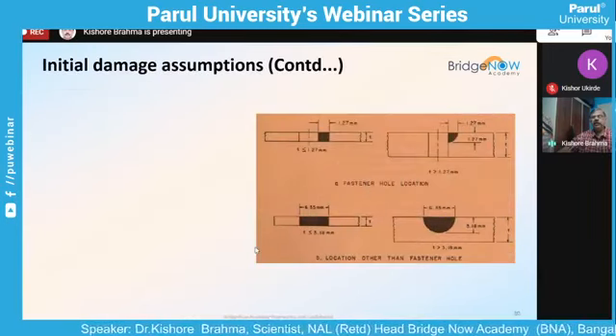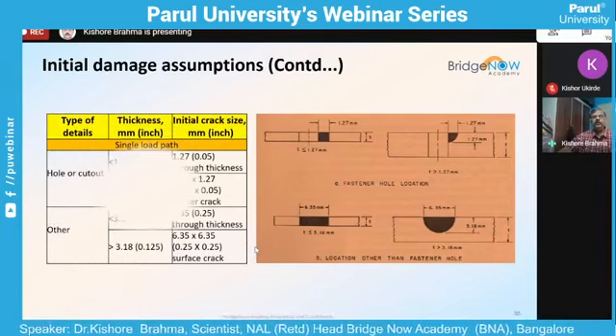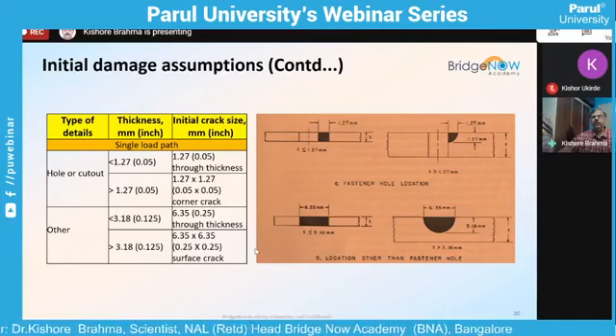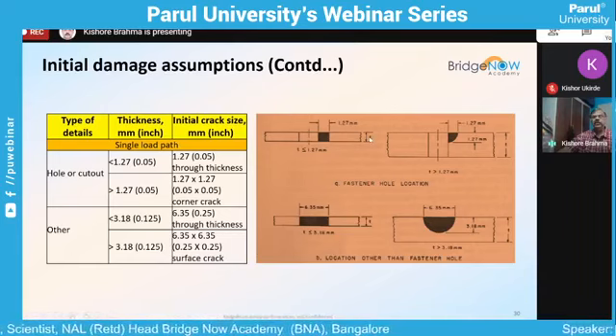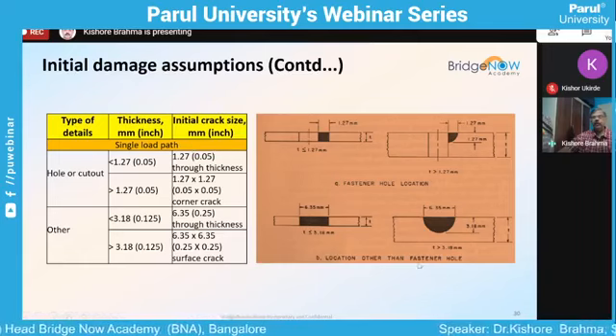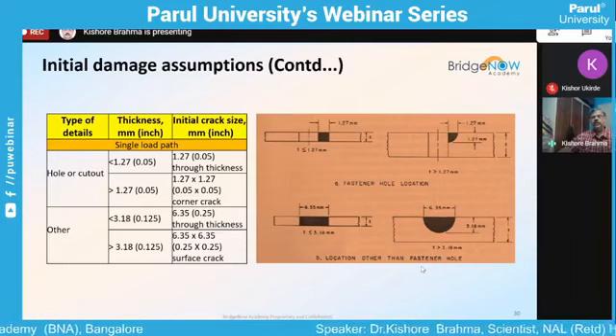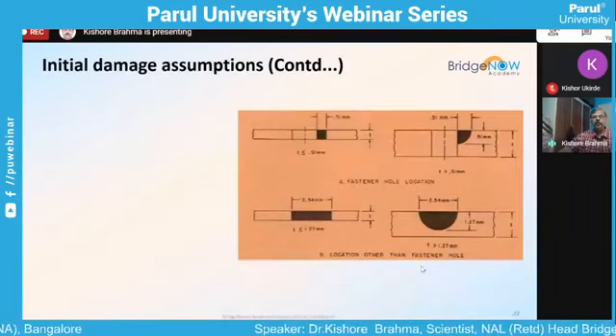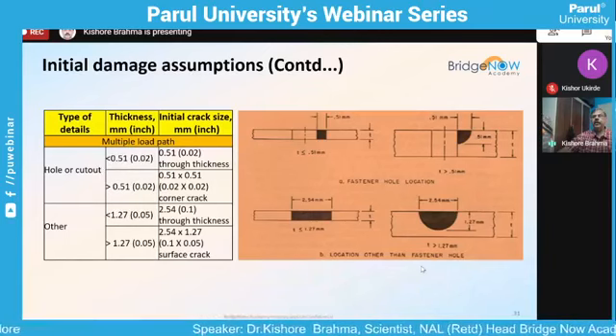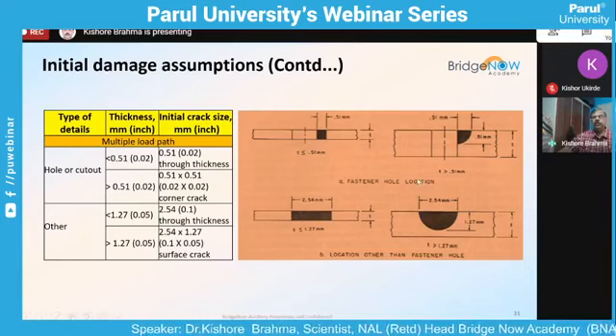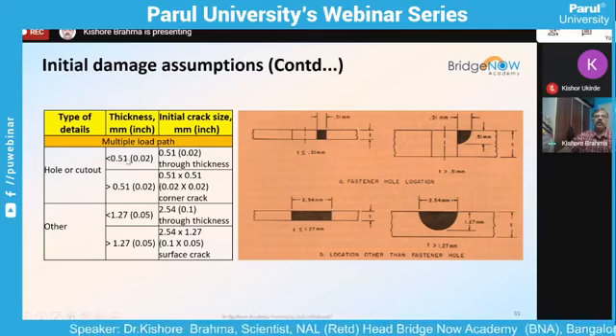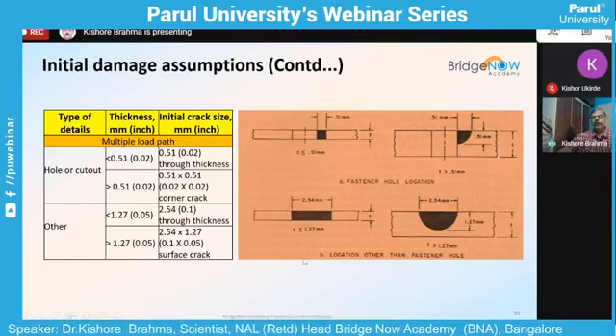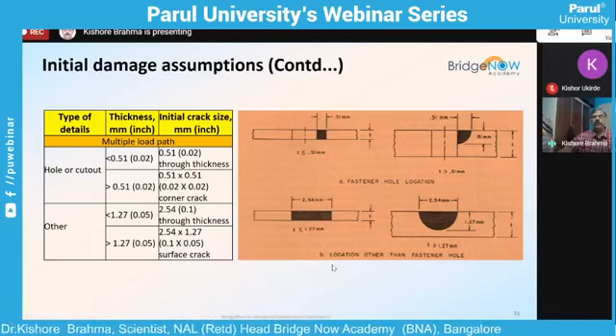Based on that standardization, you have two types of cases. You have a single load path, where the major load passes through a single load path. If you have a hole or cutout or other areas, depending on the thickness of the structure or component, one can assume the initial crack length. This is all standard and can be used, and it is required to assume this to do any crack propagation calculation. Similarly, for multiple load paths, where load can be transferred from one end to the other through multiple load paths, again based on the thickness, different initial flaw sizes are assumed. So this is the basis for doing your damage tolerance analysis.